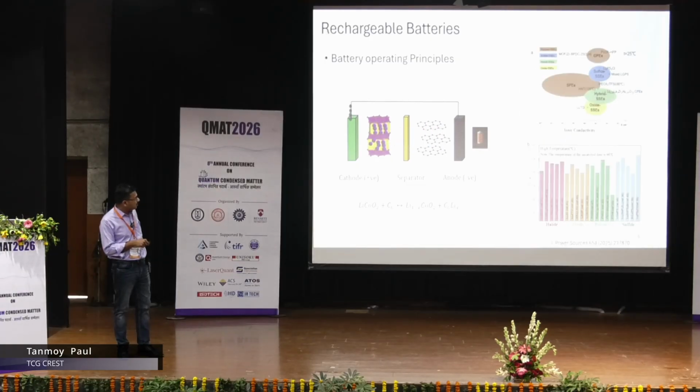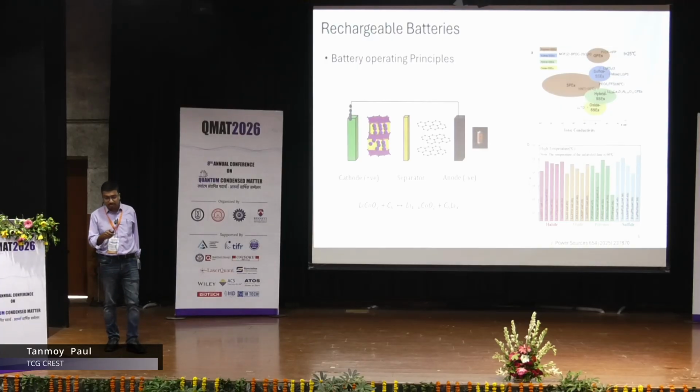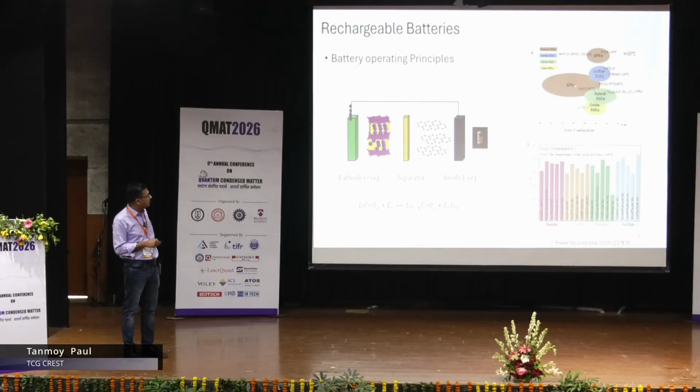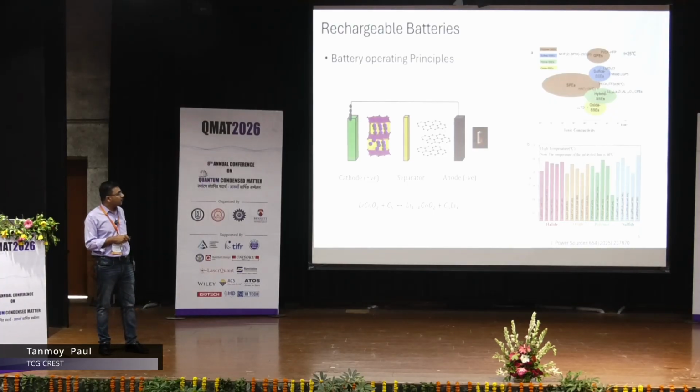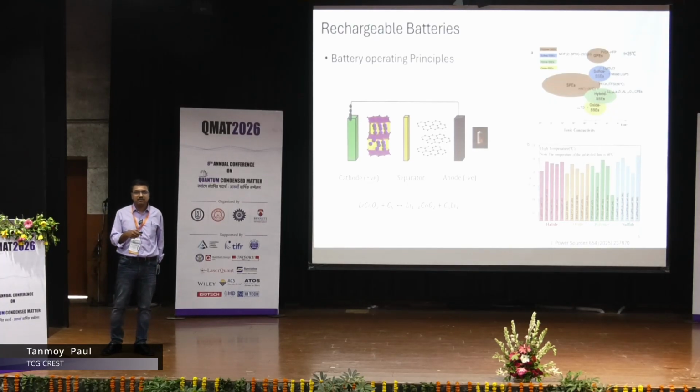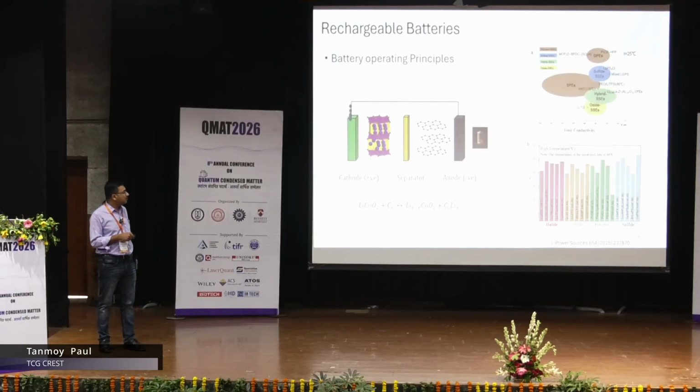In terms of solid electrolytes, people mostly think about the safety point of view, so there are different kinds of materials that people have used. There are polymer solid electrolytes, gel polymer based solid electrolytes, hybrid polymer electrolytes, and also oxide based solid electrolytes like LLZO, lithium lanthanum zirconium oxide, and hybrid solid electrolytes. Most of them have both pros and cons.